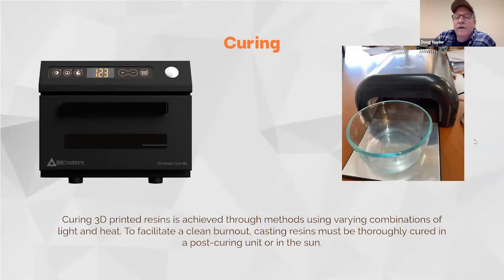Because if you don't cure your resin before casting, it's going to have a weird effect on the surface, because that surface is going to react with the investment, and you're not going to be happy with it. And that's another thing that you want to be able to identify when you look at your castings and say, okay, is this an inclusion? Is it porosity, or is it a bad surface because my model wasn't cured before I went into casting? If it's not cured, that resin is going to react with the surface of your investment, and it's not pretty. So you got to learn how to identify that as well.